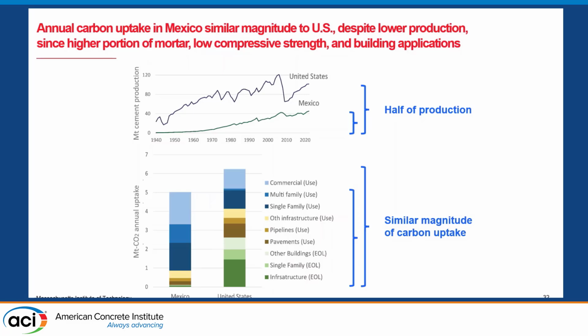And we found a similar trend comparing Mexico and the United States. The first plot is cement production over the years, and Mexico has about half the amount of cement production, but a very similar magnitude of annual carbon uptake, mostly because the cement is being used in higher proportions in these mortar applications, lower compressive strength applications like single-family and multifamily uses, which are represented in the blue bars, and building applications.